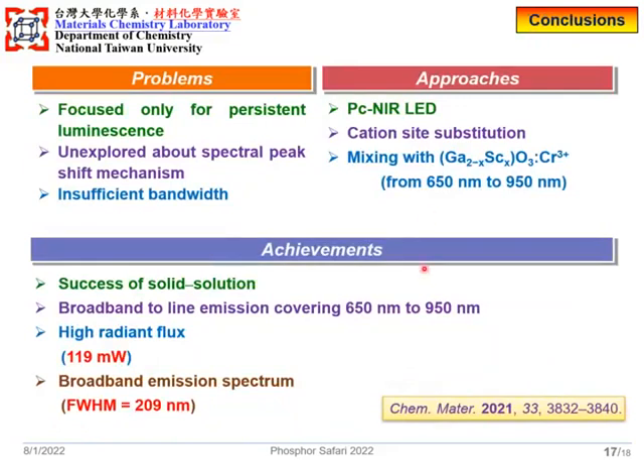In conclusion, our research achievement is the success of the solid solution and broadband to line emission covering from 650 to 950 nanometers, and we also got a high radiant flux and broadband emission spectrum.